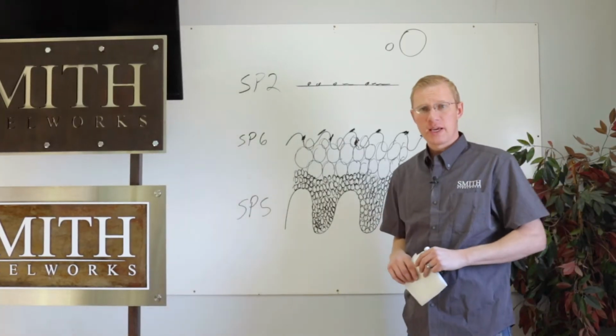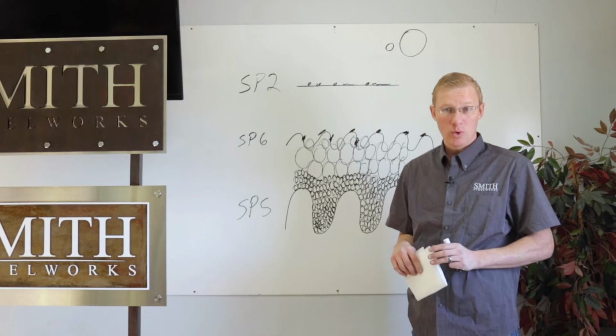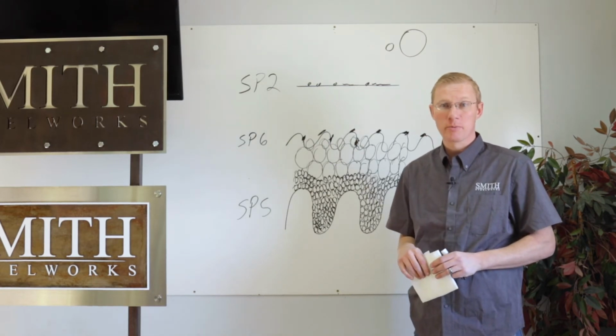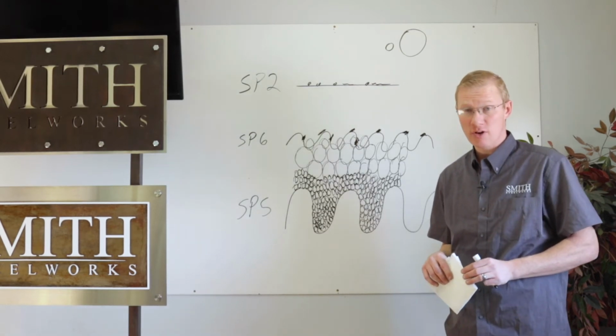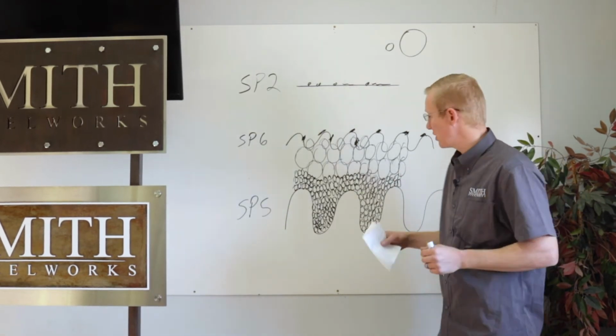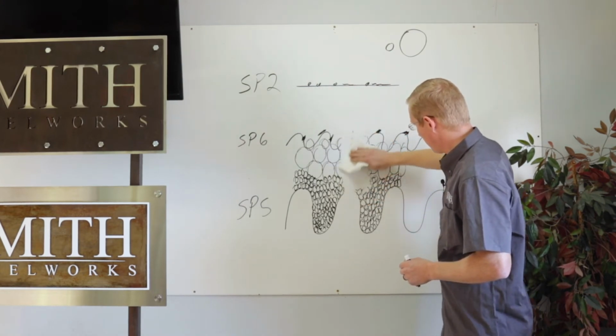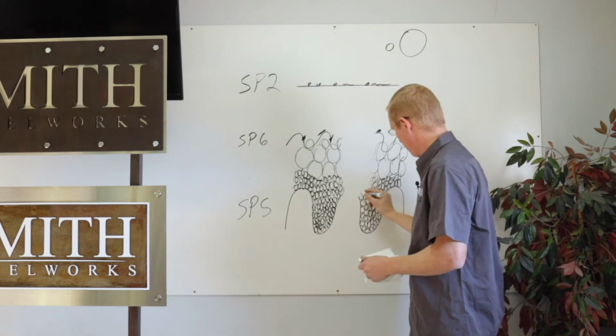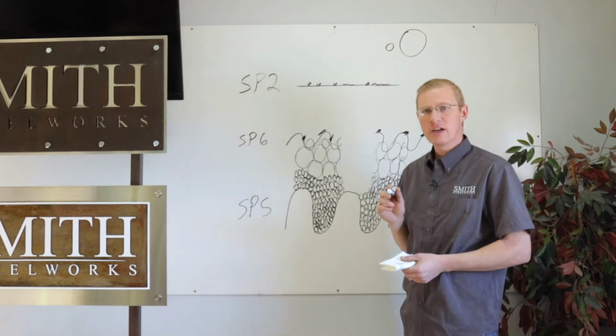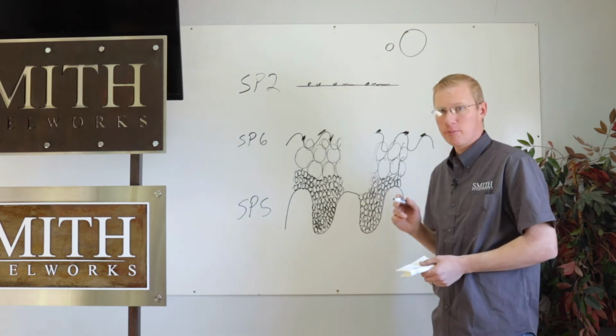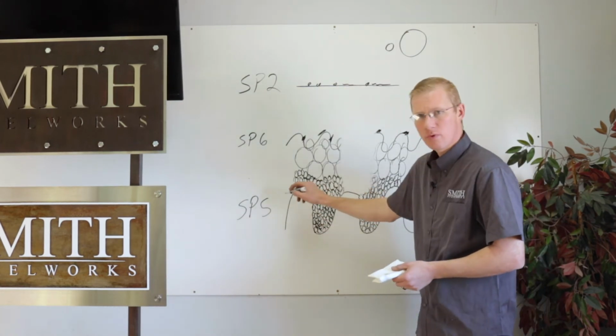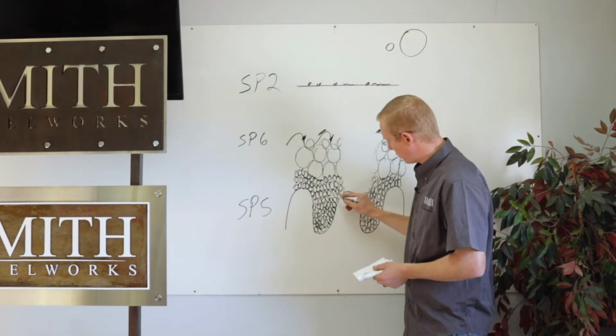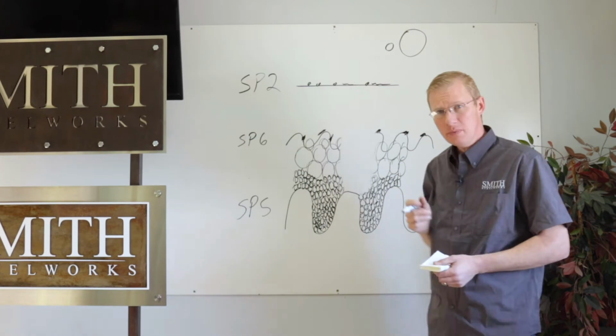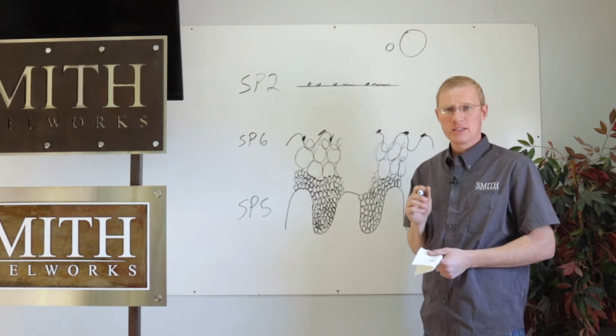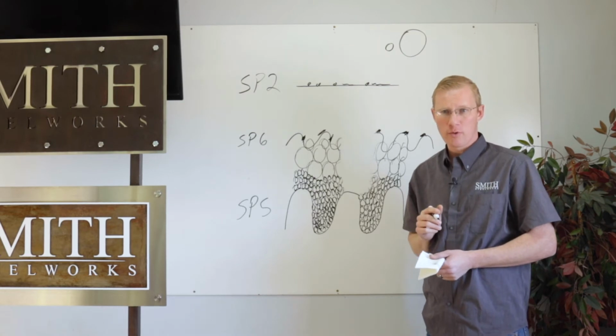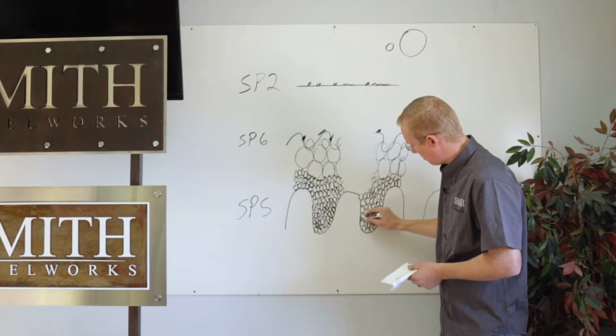When followed, the process of sandblasting to SSPC SP-5 NACE white metal finish, priming with a small molecule primer, and powder coating with a super durable TGIC polyester top coat, rust creepage will still occur when the finish is scored down to a bare metal. However, it occurs at a very slow rate. This rate of creepage is slowed by the distance of travel, as well as by the bond created from utilizing the small molecule primers. Blistering is also dramatically slowed because of the difficulty of water penetration and corrosion formation at the point where the substrate meets the primer.